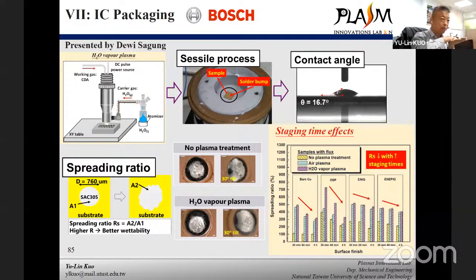So the copper oxide will be easy to be removed. With the plasma treatment, the solder will have higher spreading ratios, which means you have higher areas. So you can see without the plasma, the area is small, but with the plasma, the area is getting larger, which means that you will have good bonding between the solder and the substrate.